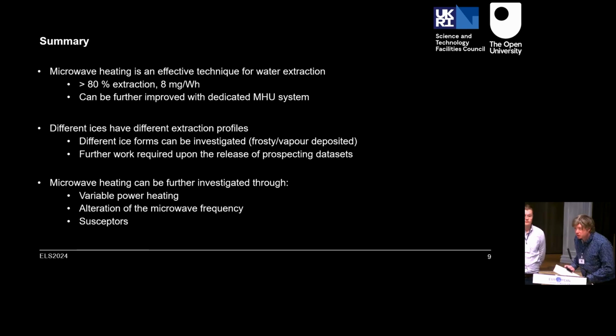If there are no immediate questions, I have one. It looks from your setup like you use a stationary positioning for the sample in the cavity. Yeah. And you use standing wave patterns. Do you have to worry about hot spots and cold spots in the standing wave pattern? So we calibrate the microwave beforehand, where we can analyze where the hotspot's going to occur, and then it occurs at a fairly consistent placement. So we place the sample on ceramic plinths that raise it to the correct height. But yes, if you were going in between those, you'd get much worse heating profiles.